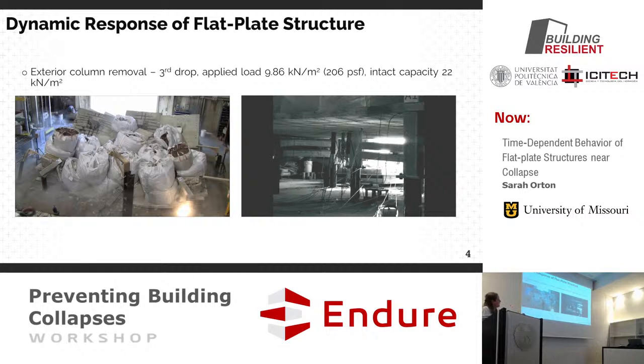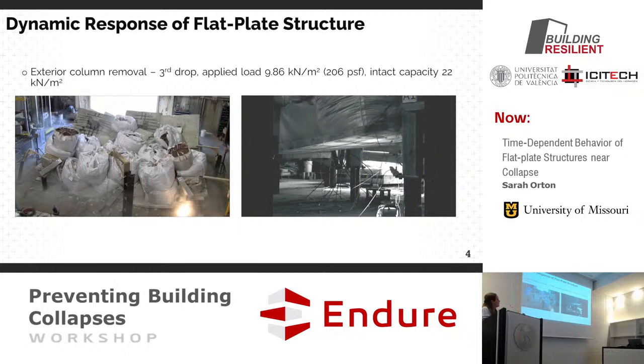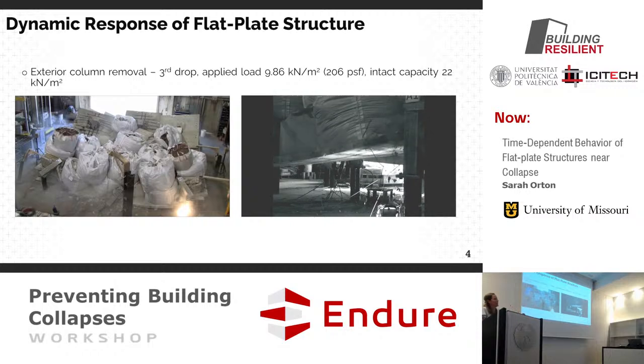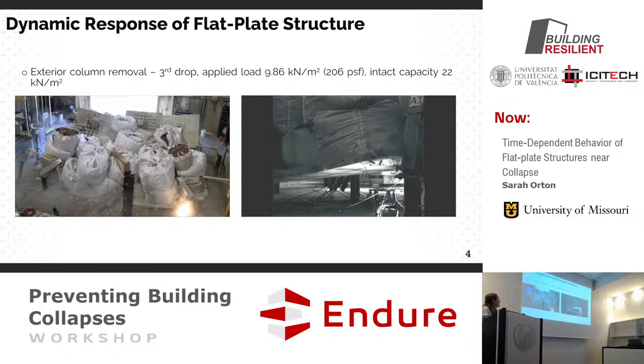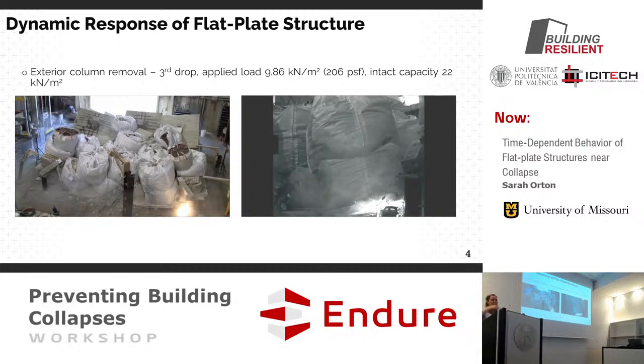This other video is a slow motion video, and so the removed column is over here somewhere just off the screen, and then we're focused on the center column, and there's some LVDTs. The slab is right in here that you can see. And so it gets removed, and you see a nice punching shear failure. It looks clearer when the contrast is a little bit better, and then everything's dropping down. And so very nice video evidence of how it drops, the speed, and the fact that it doesn't drop completely uniform. There is a little bit of rotation in it.